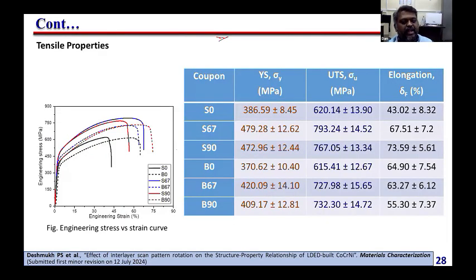And also if you take the mechanical properties, for example in the scanning direction and building direction, they are totally different. In the scanning direction, it is giving a better yield strength, but ductility is very low. But in the building direction, the ductility is much higher, but strength is less. If you go for 67 and 90, in almost all cases the strength is increasing. 90 is also giving better strength, but in terms of isotropic properties, the 67 is giving better results. So we are getting better results from the 67 sample.